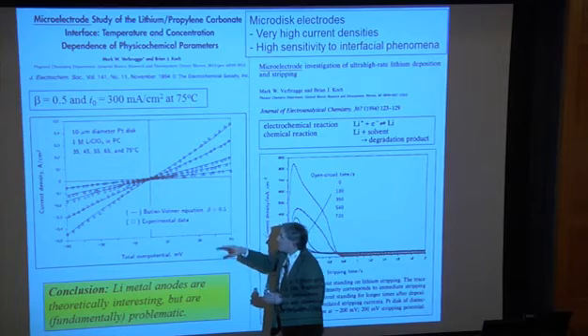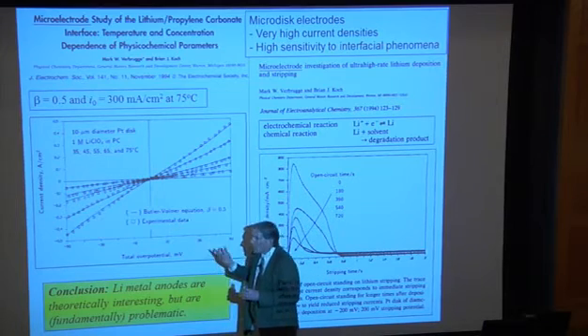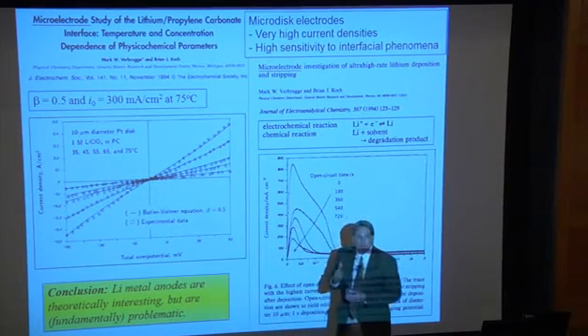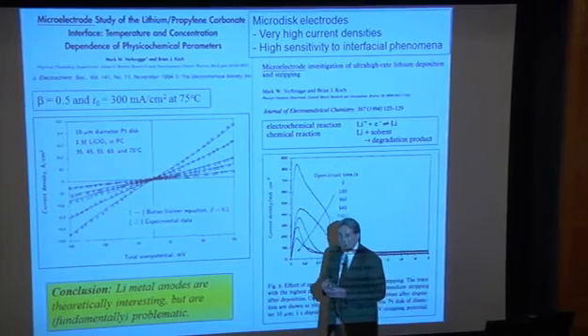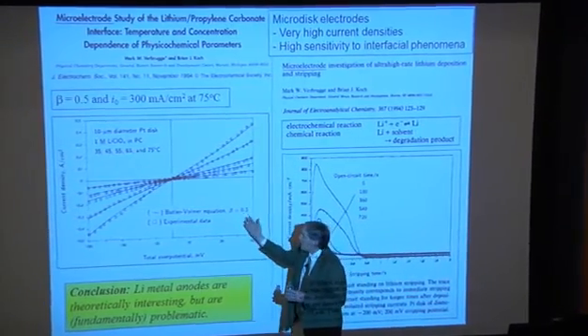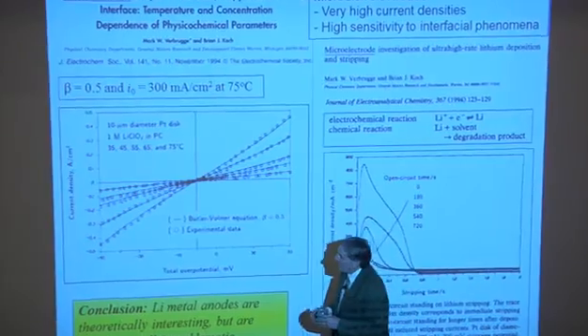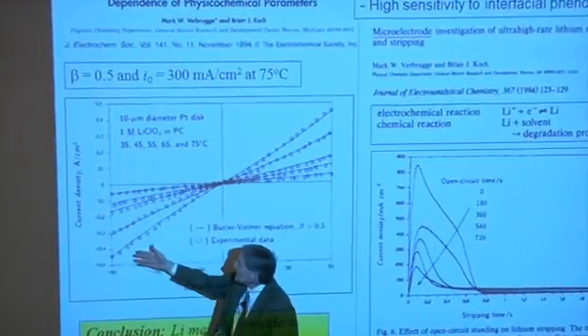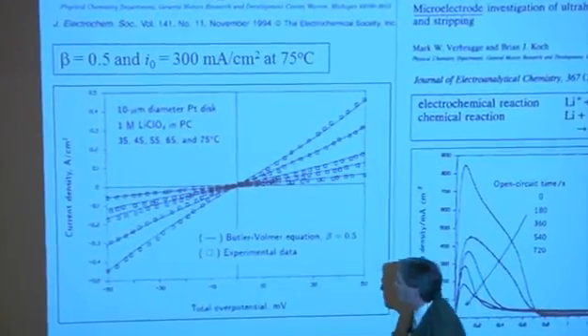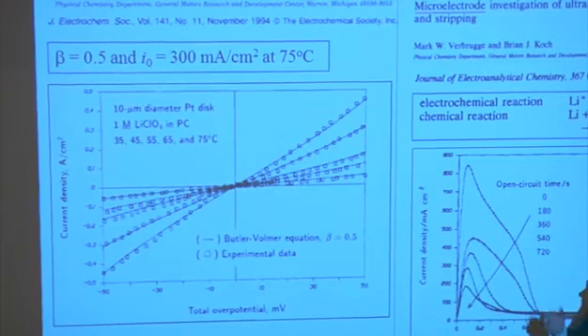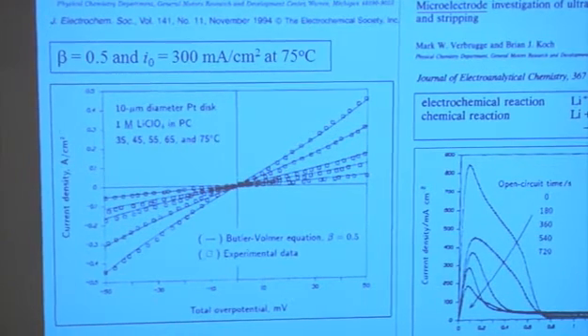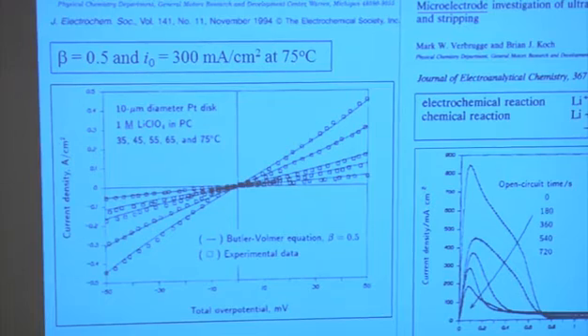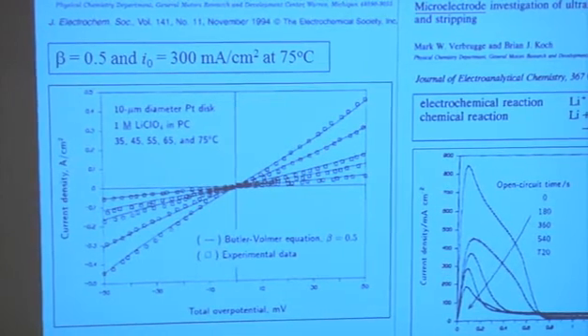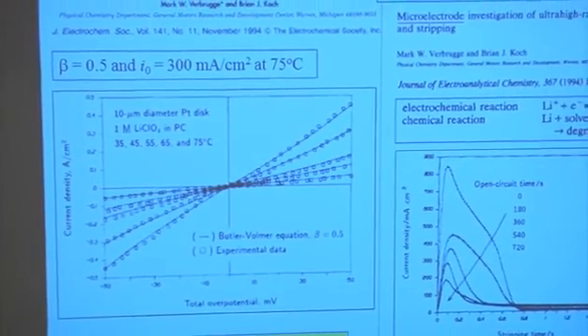And for those who work in this field, there's an equation, the Butler-Volmer equation, that's often used to model interfacial phenomena for charge transfer reactions, and it works out quite well that way. And you can see the exchange current densities that are backed out from this system are extremely high. 300 milliamp per square centimeter at 75 degrees C, that's an enormously high value. So you could say there's a lot of promise in using a lithium metal negative electrode, because real fast kinetics